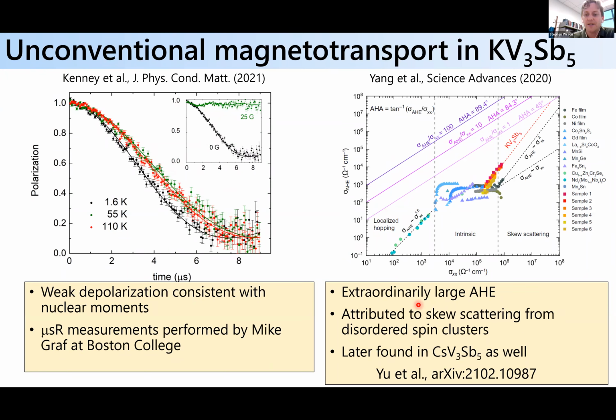I'll just add, this is not chronologically correct, but later this anomalous Hall conductivity, the same sort of magnitude, was observed in the cesium vanadium 3 antimony 5 system as well. So it seems to also be a generic feature of the materials. And I'll just add that this anomalous Hall effect turns on below this T star, or this 80 Kelvin transition that I showed you in potassium vanadium 3 antimony 5. So it seems to turn on below this phase transition that I described earlier.